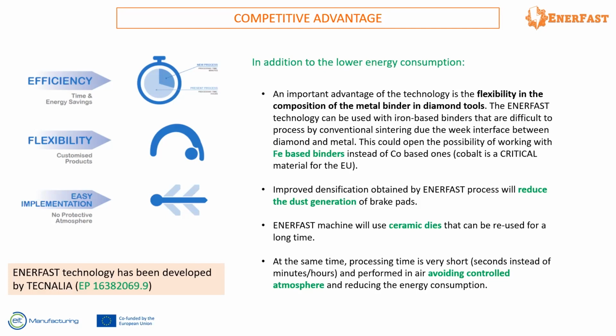It's also possible to work with iron binders. In metal diamond tools, the conventional material is cobalt, and we know that cobalt is a critical material for health and safety reasons, and also from the perspective of the EU, the possibility of getting this material. And in this case, this technology is very useful to use iron binders.